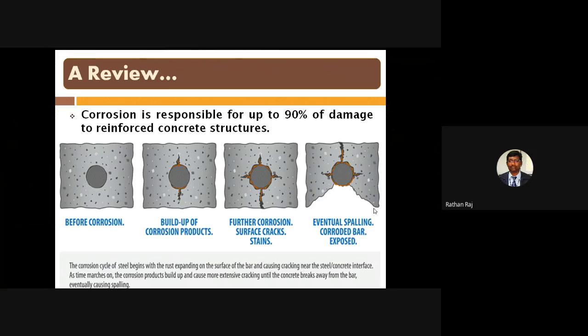So there will eventually be spalling of the concrete. After the concrete falls off, the steel rod gets corroded, and at that time we have to take more remedial measures in terms of repairing the concrete. So once any cracks are present in the reinforced concrete, the necessary care must be taken immediately to avoid more corrosion and also the spalling of the concrete. Now,